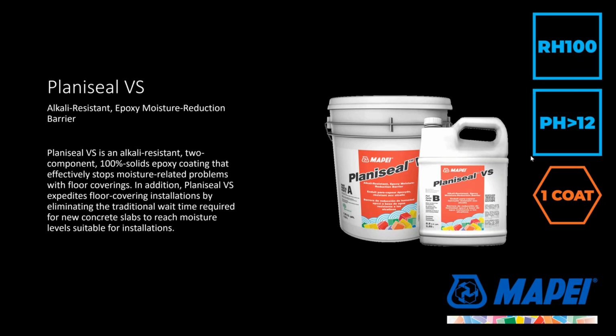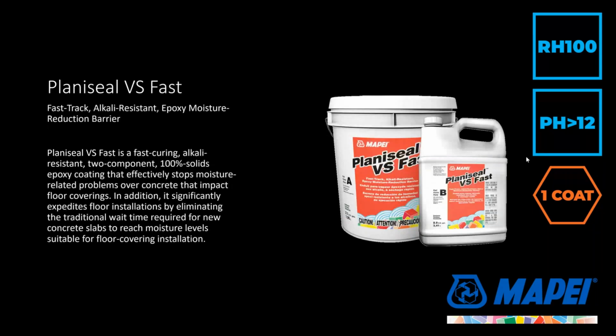Again, all epoxy products are thermoset and are affected by changes in temperature. So if it's a hot day, it's going to cure faster. If it's a cold day, it's going to cure slower. So that's something to keep in mind. Planaseal VS Fast was developed because Planaseal VS is a little bit slow. So Planaseal VS Fast does things a little bit faster. Again, RH is 100%, 25 pounds moisture vapor emission rate, pH is up to 14, one coat solution, but will cure up in about 4 to 6 hours rather than the 6 to 8 hours of the other product. So if you're trying to get something done a little bit quicker, this is the way to go.